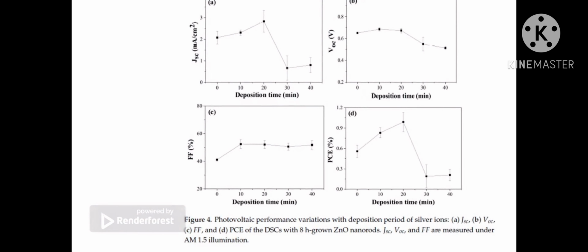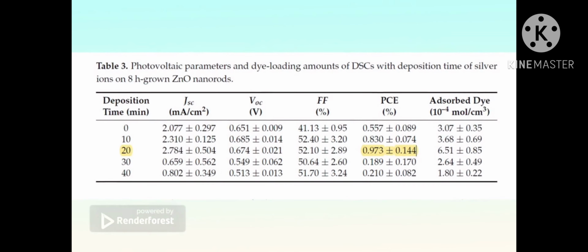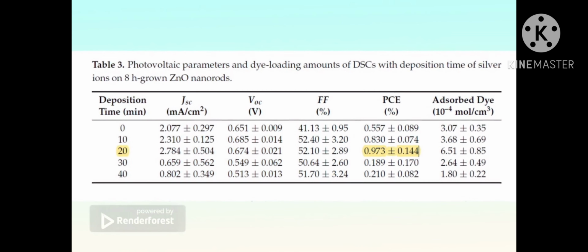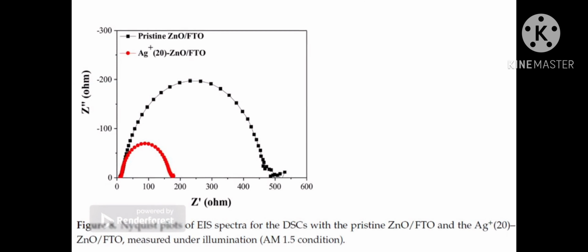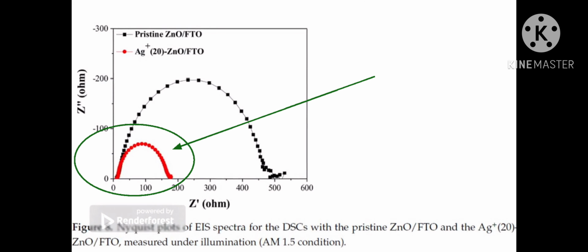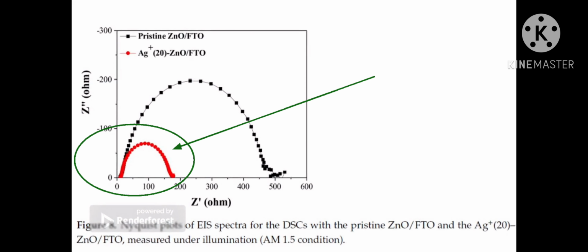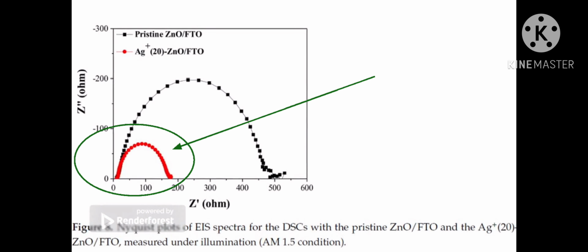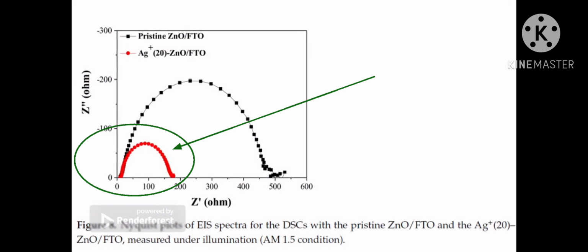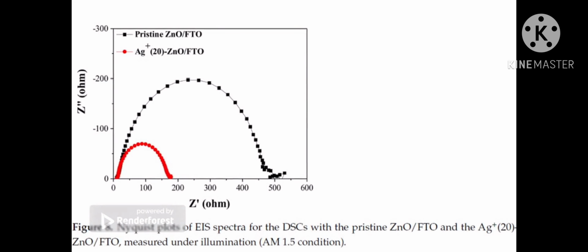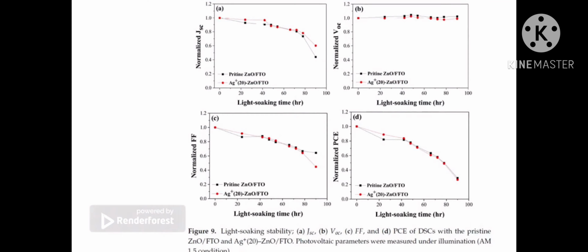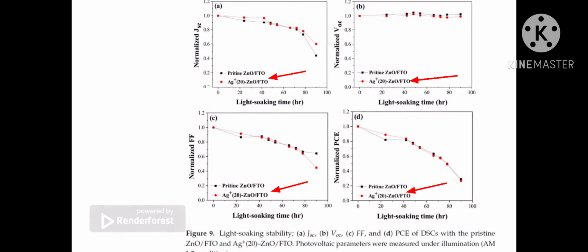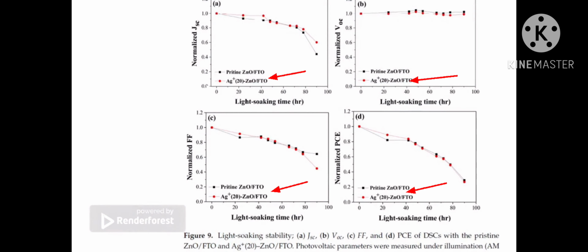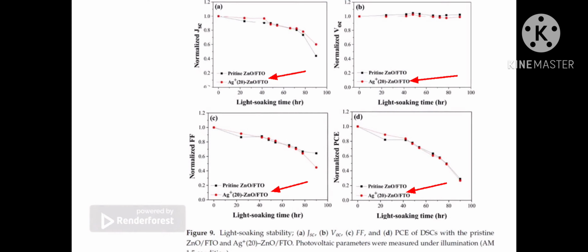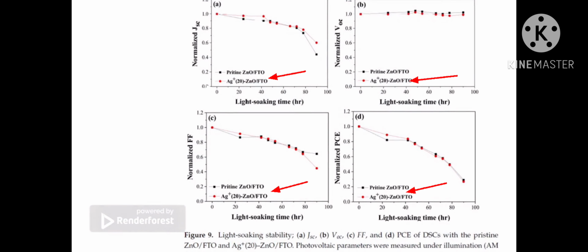From figure 4 and table 3, we can understand that at 20 minutes the PCE has the highest value. From the next plot, we can see a decrease in the diameter of the semicircle of the silver ZnO/FTO, which indicates that the resistance or impedance decreases. This is clearly shown in figure 9, the time-dependent performance variation of the cell, indicating the silver ions did not affect the device stability.